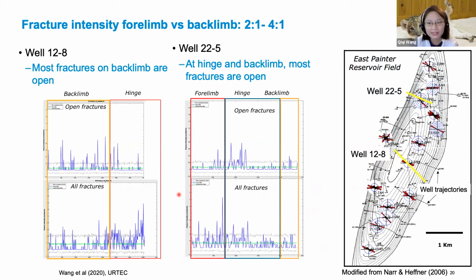In terms of fracture abundance, our first key finding is that the overall fracture intensity in the forelimb of the fold is 2 to 4 times higher than that in the backlimb. However, we want to be careful because in the hinge and the backlimb, although the fracture intensity is high, many of the fractures are sealed. For example, the well on the left, the fractures on both the hinge and the backlimb of the anticline here, I'm showing the fracture intensity. And please see the intensity of open fractures versus all the fractures, right?